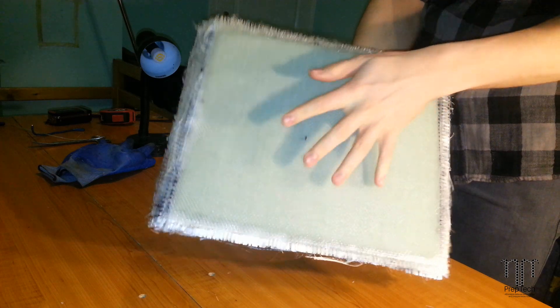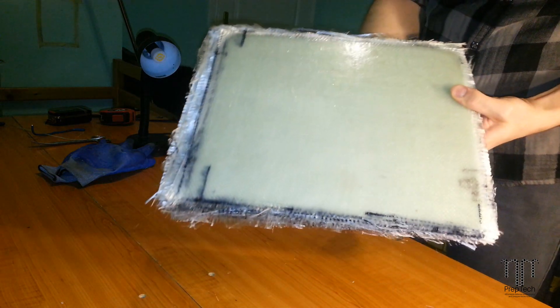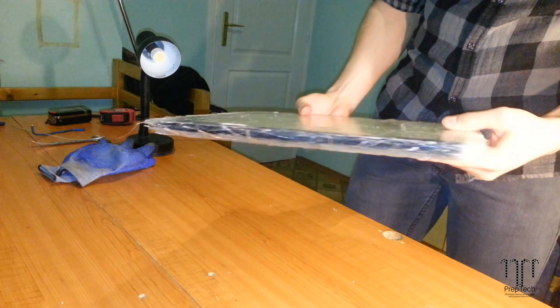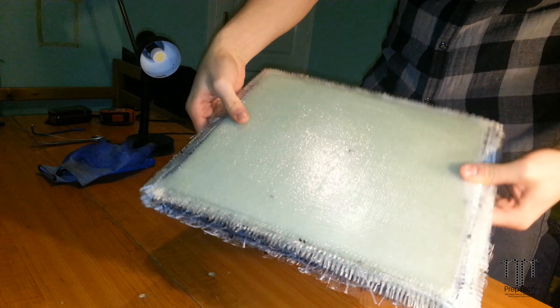It was very hard and sounded like a tile, I've never touched anything like this before. The final thickness was 1.6 cm, which is better than I expected and it weighs 3.4 kg, which is on the other hand a bit worse than I calculated. Surprisingly, it soaked up almost a kilogram of resin.